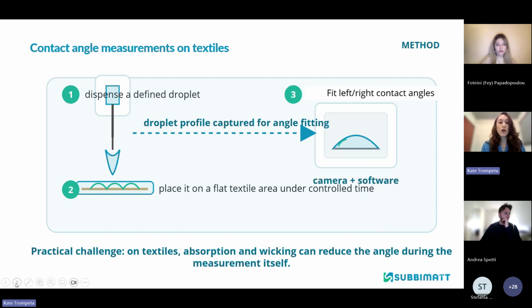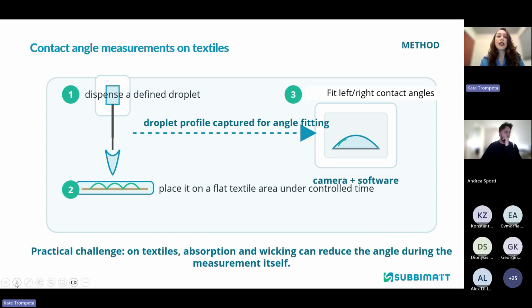We have a flat surface where we place the textile. We try to keep it flat, and then we dispense a definite droplet. We need to calculate the volume of this droplet in order to be able to drop it and have a sessile drop on the surface of the fabric. Afterwards, we capture the droplet profile and try to fit the angle with specific software on the machine that we have. Most of the time we have to fit both the left and right contact angle.